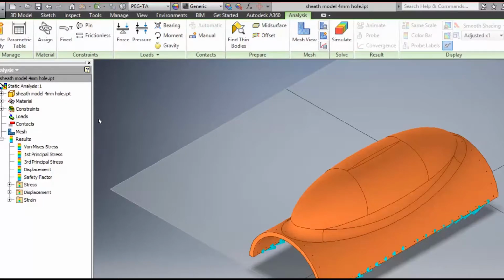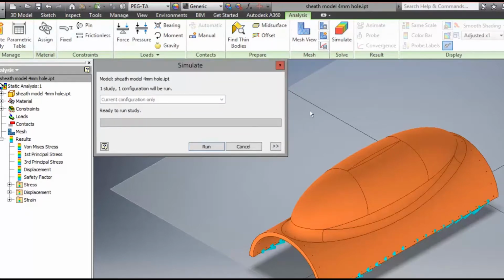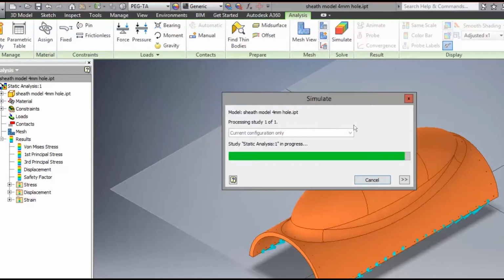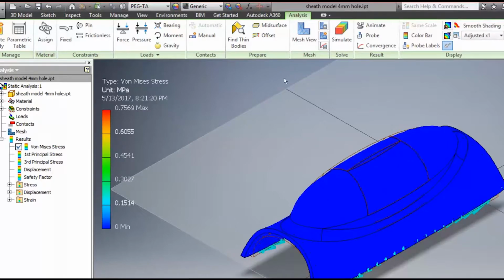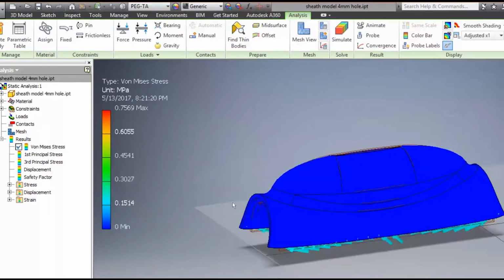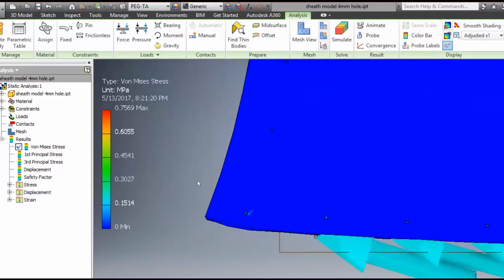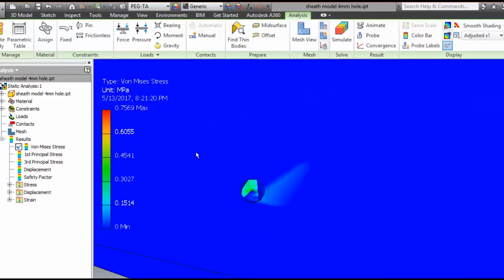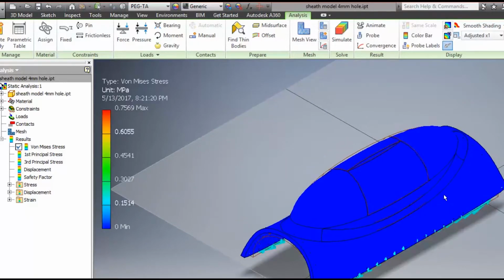We supplemented our in-lab techniques with computational modeling in the form of finite element analysis. We created a 3D model of the sheath here using material properties yielded from DMA. Running this model, we deformed the sheath to the maximum radius of curvature of the human spine, or 30 centimeters. Examining the model, we can see that the von Mises stresses are concentrated on the outermost suture hole, and they're exorbitantly larger than the compressive failure stress yielded in DMA. This led us to conclude that our model would be best suited for a patient that is stationary during recovery.